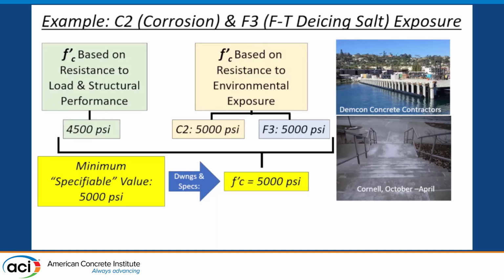So let's take a quick example here. We've got C2 corrosion, we've got F3 freeze-thaw, and let's say the structural engineer designed it for 4,500. When the design calculations were done, 4,500 was picked. If we take a look at our C2 and our F3, that says 5,000. So what was supposed to happen here is you say, all right, I've got a strength and mechanical properties requirement, I've got a durability requirement, the highest requirement is going to govern. So we've got a minimum specifiable value of 5,000 psi for a structure that maybe looks something like that.